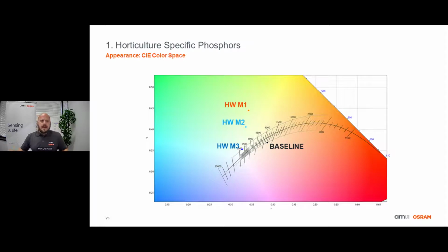Now, some of you may have looked at the resulting spectrums that I just showed earlier and thought, boy, those are going to look ugly and are going to look pretty red. Well, as you can see in the graph below, this isn't the case. While yes, there is a large red peak in the Horti white spectrums, this peak is at 660 nanometers, which is at the far edge of our eye's sensitivity. So it contributes very little to the solution's appearance.